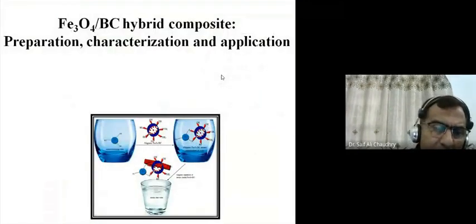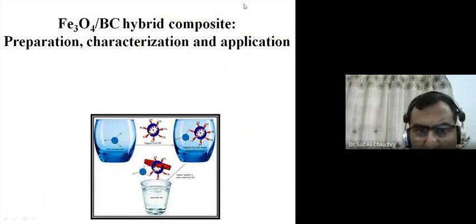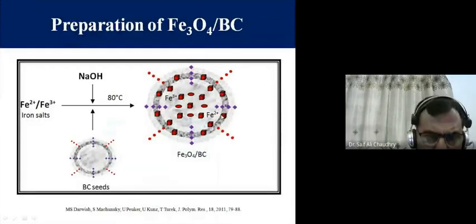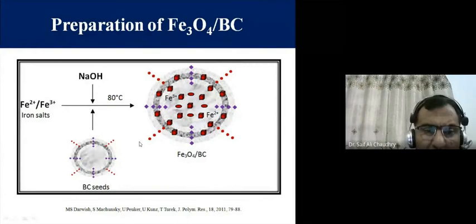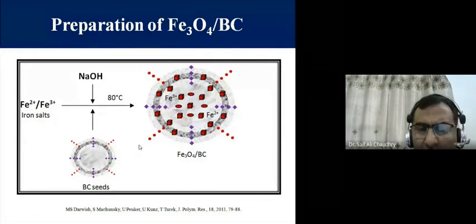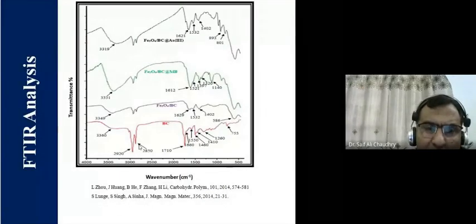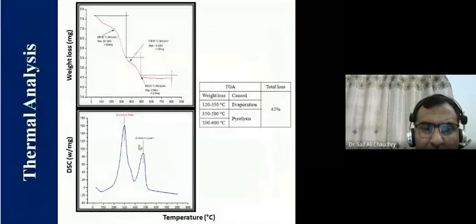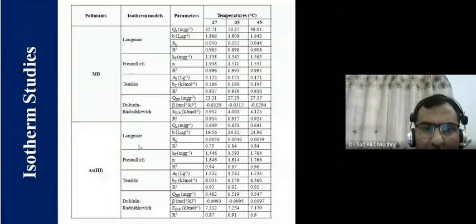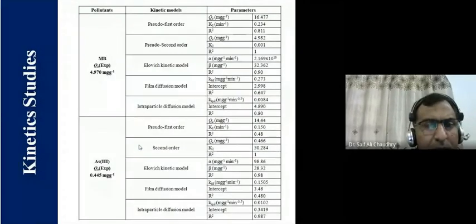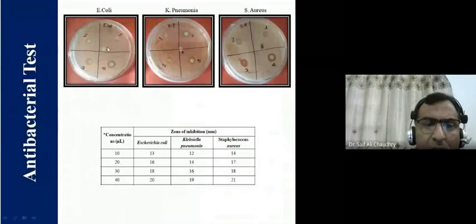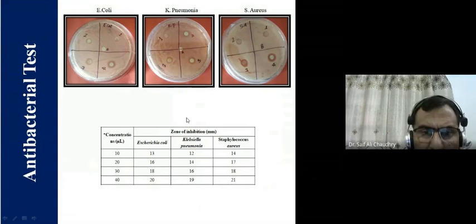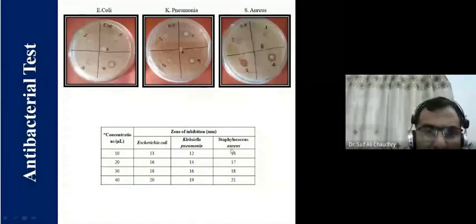Now, we have also prepared this iron oxide BC hybrid composite. The same study we have done, but with the advantage that this is a magnetic composite. We can use it and we can separate it by applying a magnetic field. So this gives advantages. Now the same type of studies we have done. I'm just showing what we are doing in our department, and again, we can control pneumonia. This table shows the effect; these materials are more effective for S. aureus, the positive bacterial strain.